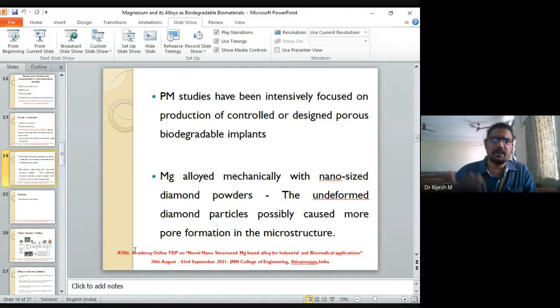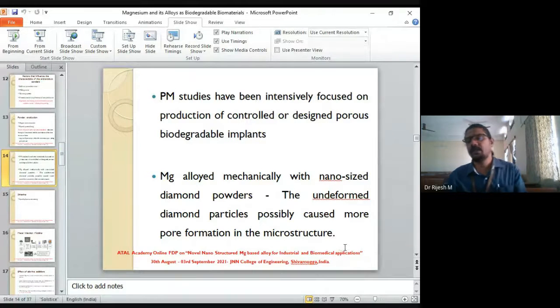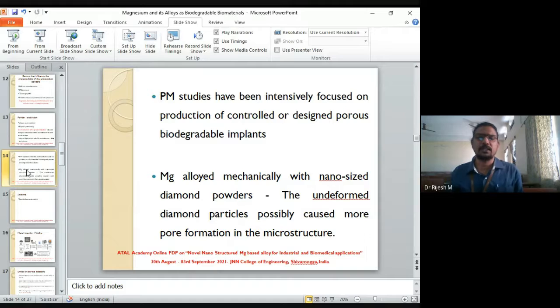There are many ways in which people do this, by coating and other things. I'm not going deep into these things, but if you alloy this mechanically with nano-sized diamond powders, undeformed diamond particles, diamond is so hard they don't get deformed, possibly causing more pore formation in the microstructure. So they will have a lot of pores.